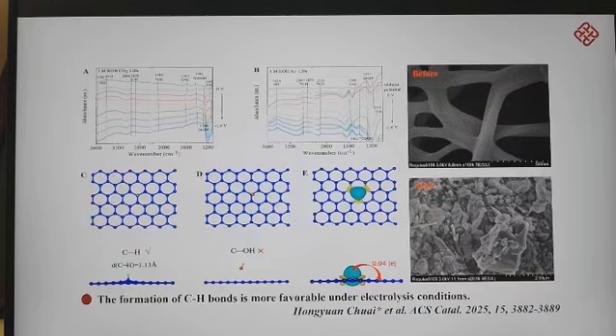In order to investigate the carbon reduction reaction, we characterized the carbon-based electrode before and after electrolysis. We can see from the SEM images that carbon fibers break into nanoparticles after electrolysis. To analyze the mechanism of the carbon reduction reaction, we used in situ infrared spectra to monitor the intermediates generated during electrolysis. The results revealed the peaks of carbon-hydrogen bond, carbon-carbon double bond, CO, COOH, OH, and other intermediates.